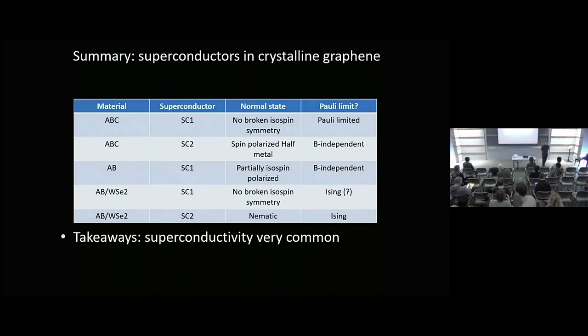Is there ever anything interesting in the temperature dependence of the resistivity at any of the places? Yeah. Yes? Yeah. Where? What? Why? I mean, we're still thinking about it. At quite high temperatures, what we've looked at so far looks very consistent with, I think Shankar has a paper on electron-phonon coupling. It looks like that. But there's an intermediate temperature regime where it actually has non-monotonicities. And we're not sure where those come from. And that's something that we're thinking about. But it doesn't have, for example, strong linear T. It has linear T that's more or less what you'd think from phonons, to within a factor of 50% or something like that.